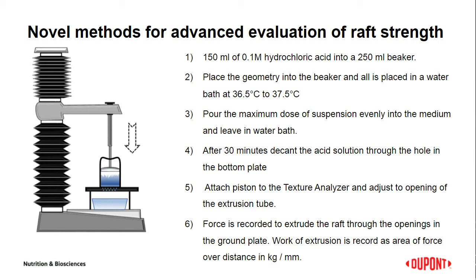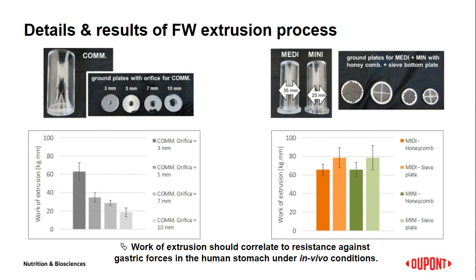The raft gel remains in the geometry and is extruded with a piston connected to the texture analyzer through the openings in the bottom plate. During the measurement, the texture analyzer is recording the force which is required to extrude the gel. Results are given as the work of extrusion, which is recorded as the area of force over the distance in kilogram per millimeter.